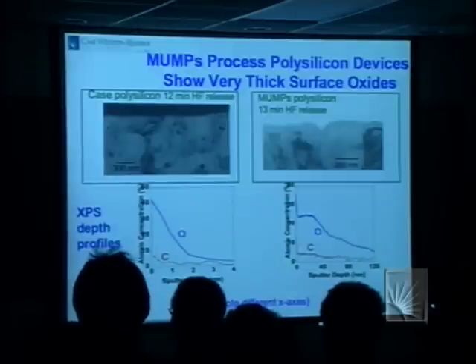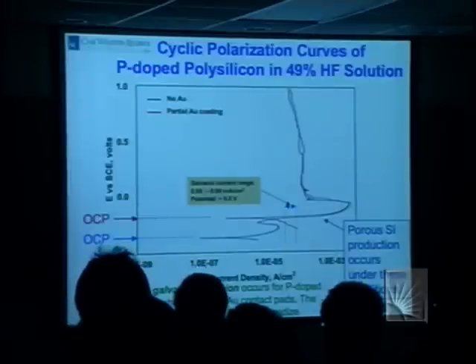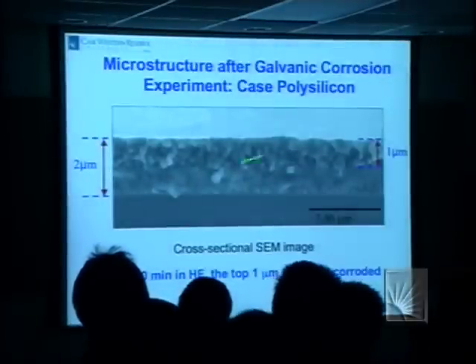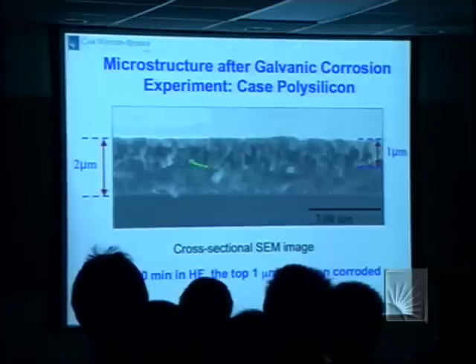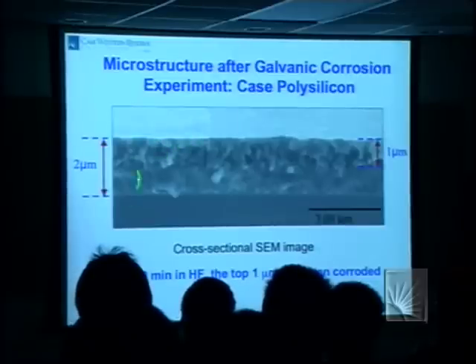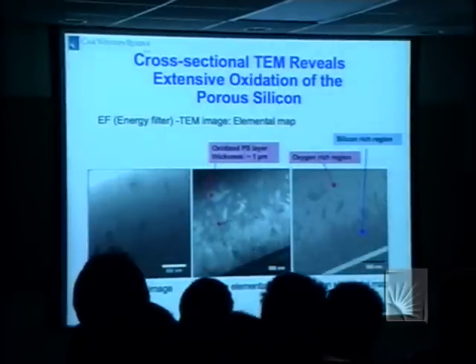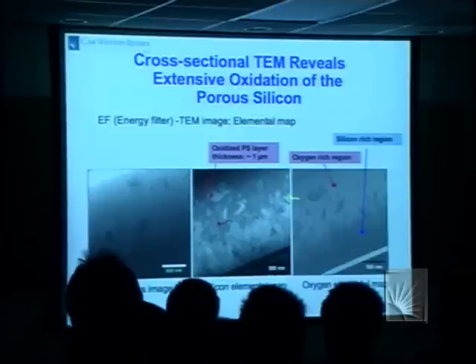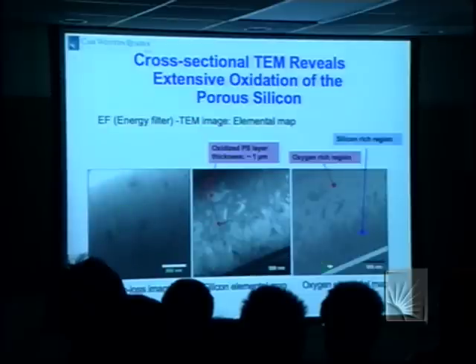And naturally, they've now gotten to a regime where silicon is no longer passivating. And we studied this in the TEM. This is a cross-section. This was the actual sample we used in this electrochemical experiment. And there's been some corrosion in the top half of this 2-micron thick film. We've done some more fancy electron microscopy, the so-called energy filtered TEM. The important thing is this is just an ordinary image. The details aren't important, but you get silicon-rich and oxygen-rich regions.